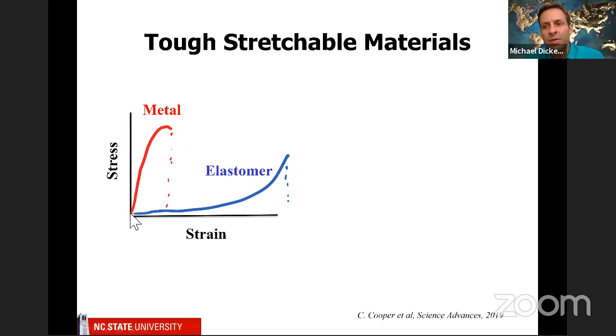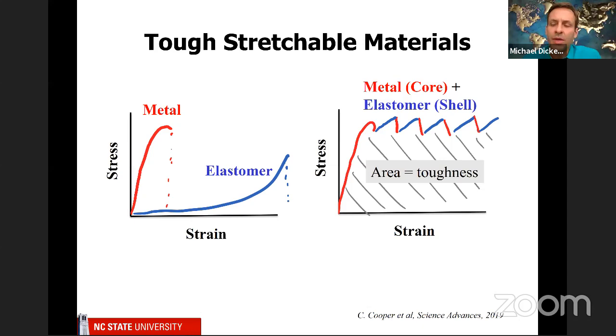A metal has a big initial slope, which means a big modulus. It's very hard to stretch it, and then at a low strain, it breaks. Whereas an elastomer goes to high strain, but requires very little stress, relatively speaking. So to make a tough material, we would like to make the best of both worlds. We would go to high stress and then high strain.